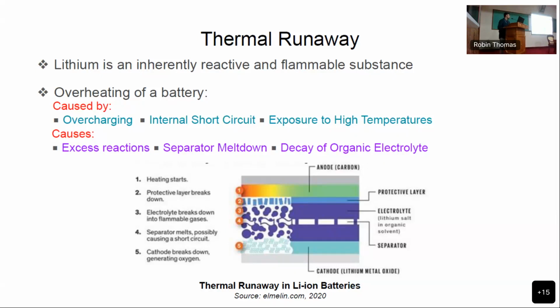And decay of organic electrolyte. This was spoken about a few slides ago, that the organic electrolyte can decompose to form combustible gases. And also the cathode is made up of lithium metal oxides. So it's possible for the oxides to release oxygen, which is a promoter of combustion. So if a small fire starts, it has a chance to spread to the parallel cells, and the corresponding cells will also start a fire, causing a chain reaction, which is called thermal runaway.